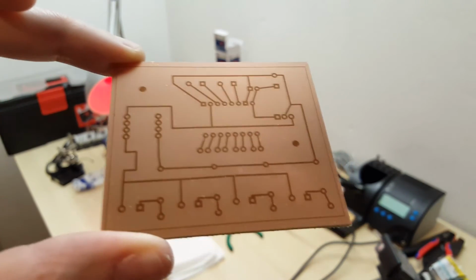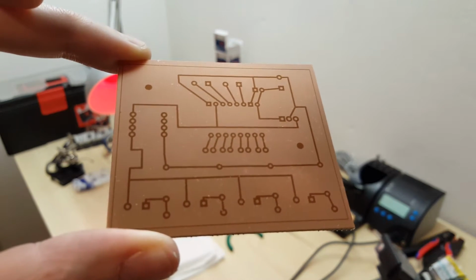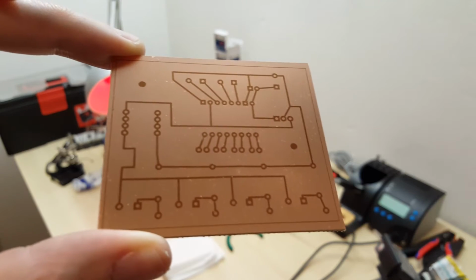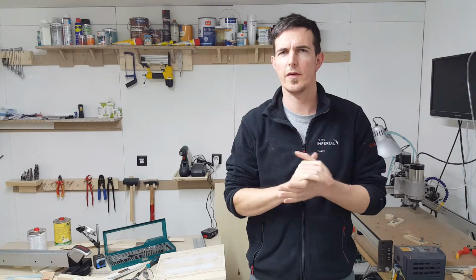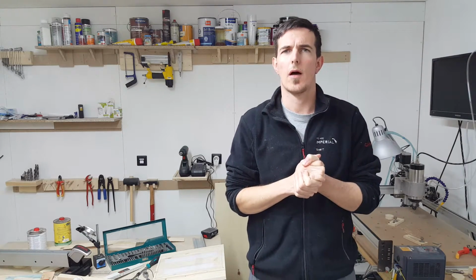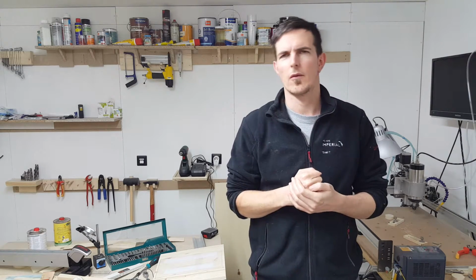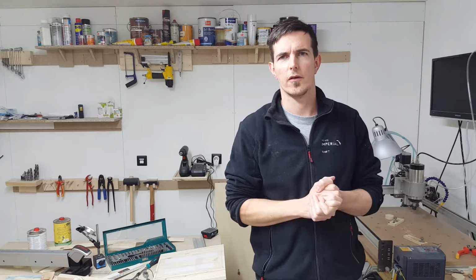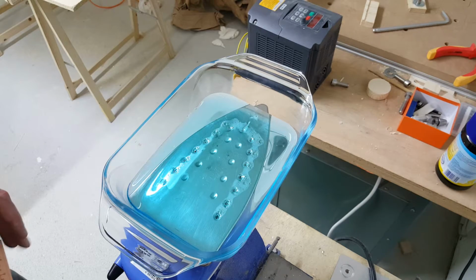Okay, the last part is to get rid of the unneeded copper. So let's go and etch this thing. Okay, for etching the copper we need some 50 degree hot water and sodium persulfate. We bathe the PCB in the solution for, I think, around 40 minutes and this will etch the exposed parts of the PCB away. So I will prepare the solution and see you in a minute. Okay, let's put the PCB in it.